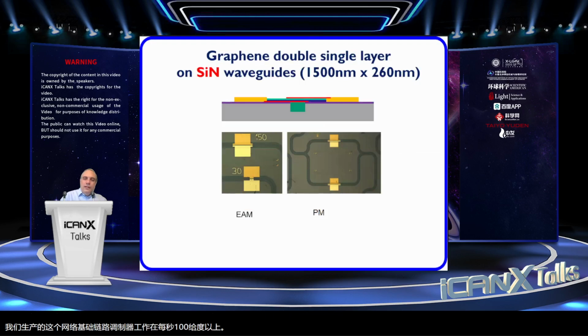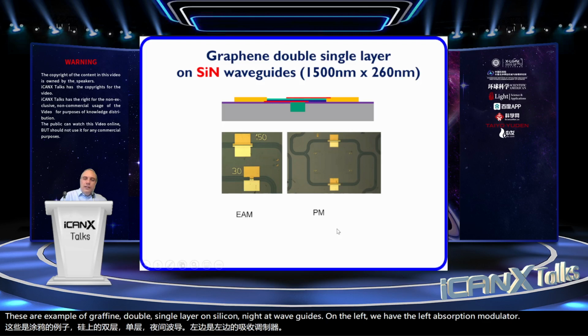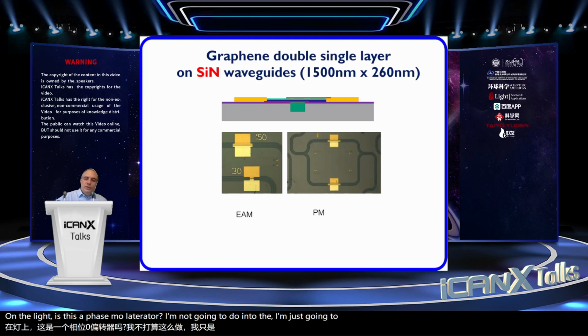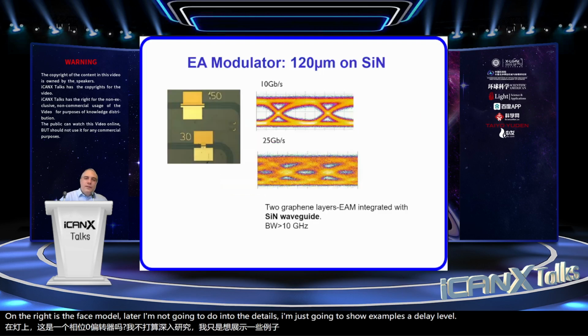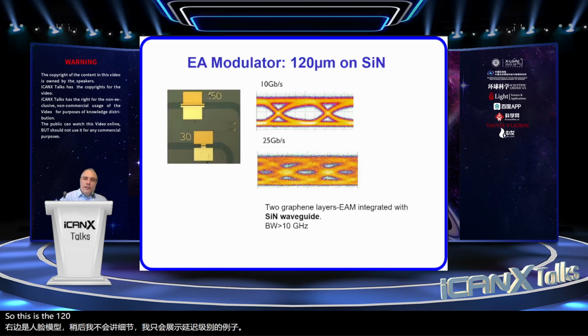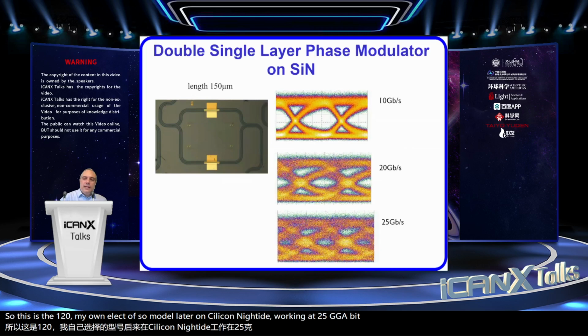These are examples of graphene double single layer on silicon nitride waveguides. On the left, we have an electro-absorption modulator. On the right is the phase modulator. I'm not going to go into the details. I'm just going to show examples at the high level. So this is a 120 micron electro-absorption modulator on silicon nitride working at 25 gigabit per second.